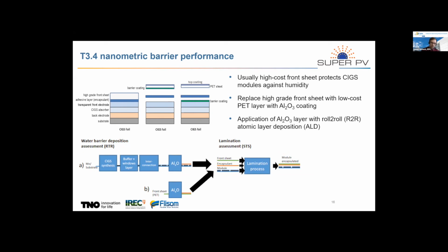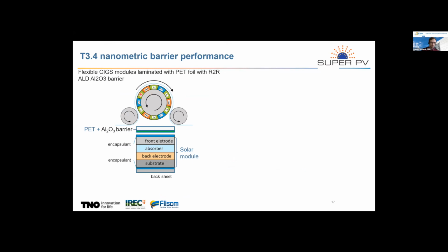The aluminum oxide layer here is deposited in an ALD, atomic layer deposition step, which is developed by TNO. They are using this roll-to-roll ALD unit. And here you can see the wheels guiding the PET or the CIGS module in the process chamber.